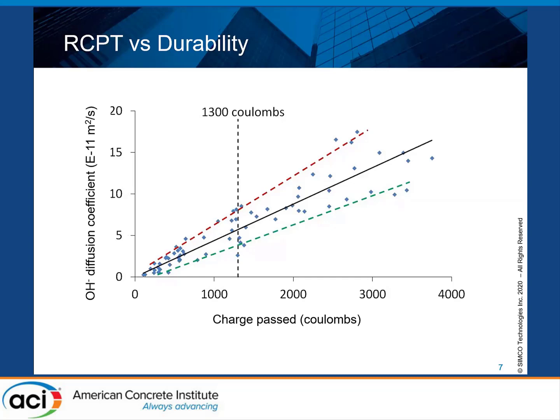But once again, if, for example, you look at 1,000 coulombs, which would be considered a good concrete, and you see in codes that value, 1,500, 1,000 sometimes, you can still get a large scatter in the results in the diffusion properties. So as I mentioned, don't pay attention because it's the OH diffusion coefficient here, but it's directly proportional to the chloride diffusion coefficient. So maybe the scale is not something you're familiar with, but the scatter is still there. The point is that if you're relying on compressive strength, you may get a wide scatter. If you're relying on RCPT, it's smaller, but it's still not a direct indication of the durability you may get.